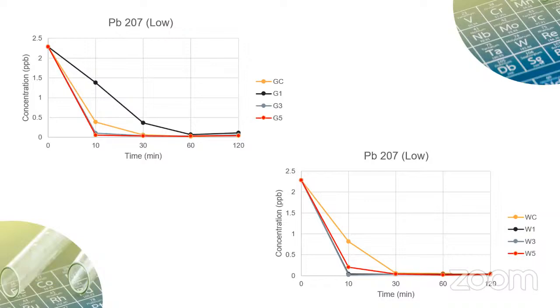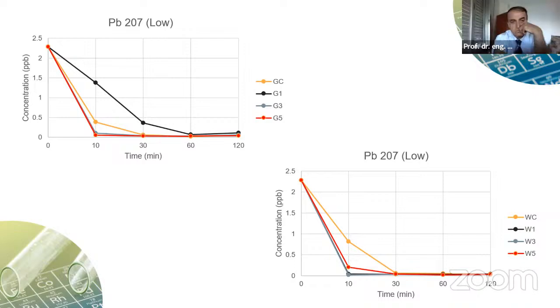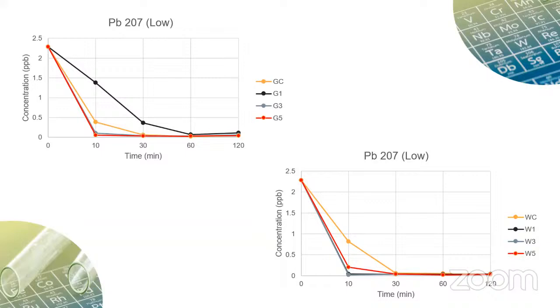As for heavy metals, also samples were taken at certain time intervals, and they were tested using the ICP-MS. It was obvious that we had a decreasing trend and approximately above 95% removal of most of the heavy metals. Definitely some were not responsive to the photocatalyst, but several heavy metals were highly responsive, and we achieved the maximum drop at 120 minutes, and the mixes containing 5% titanium were the most efficient in the absorption of heavy